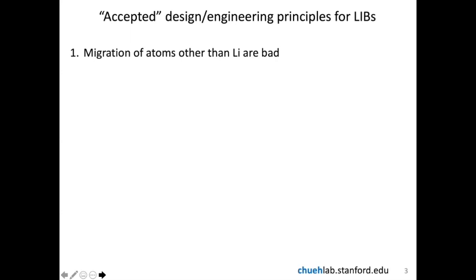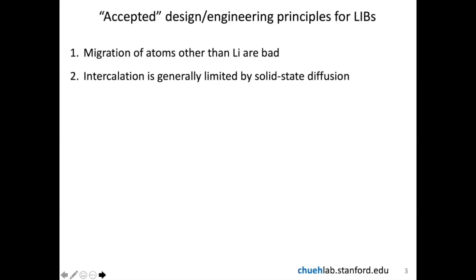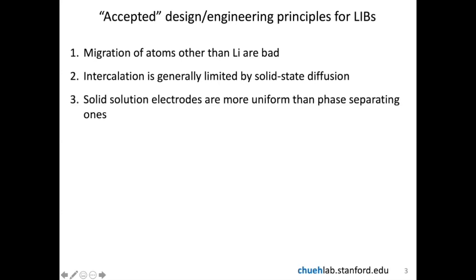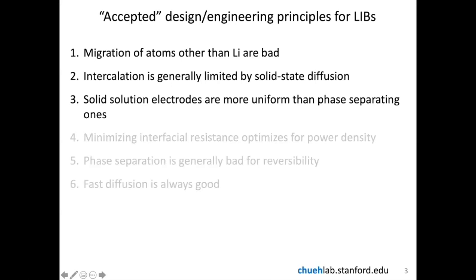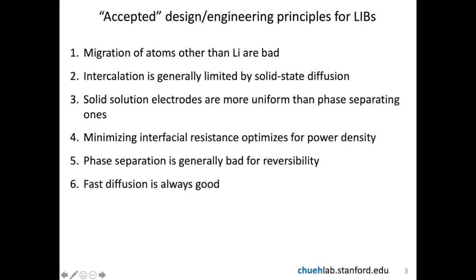So the first design rule I want to talk about is the atomic level disordering of the material. It's usually believed that migration of atoms other than lithium is problematic for lithium-ion batteries, especially at the cathode. And the second design rule is that intercalation is generally limited by solid-state diffusion in the cathode materials, and minimizing interfacial resistance, for example, at the cathode electrolyte interface, optimizes for power density. Phase separation is generally bad for the lifetime of lithium-ion batteries. So I'll come to each one of these in the next half an hour.